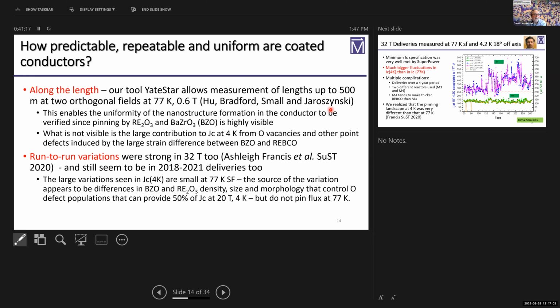And so, the other issue is that the internal chemistry of these conductors has been a wonderful playground where you put nanoscale precipitates into the material and things like that. But the difficulty about this is that when you're growing such a film at 750 centigrade or thereabouts, you have to utterly control the nucleation of what's growing. Otherwise, you don't get something consistent. And maybe I could make this point, that this is what happened.